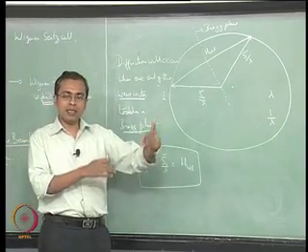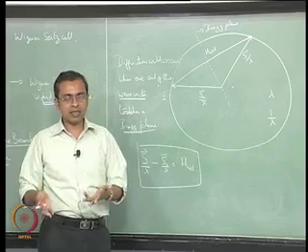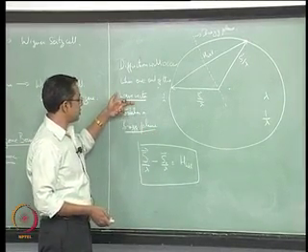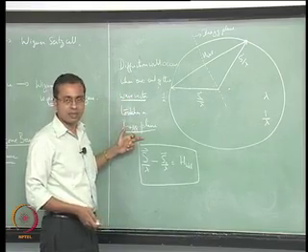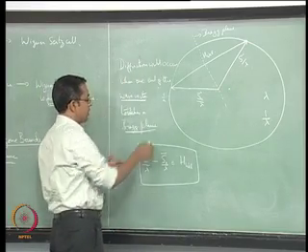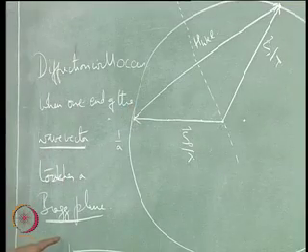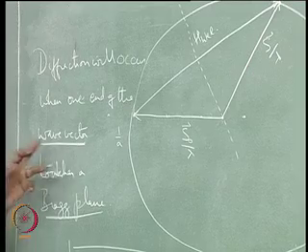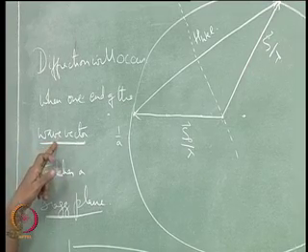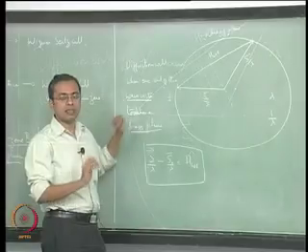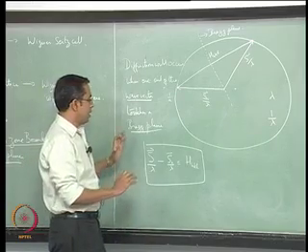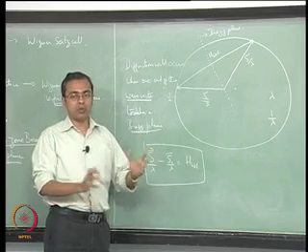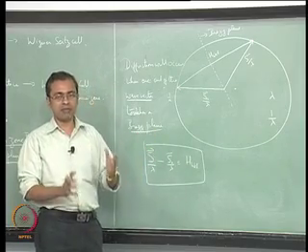Another piece of information is waves that are arriving at the sample or are in the sample. There are wave vectors with respect to those waves. So this is something associated with the wave, this is something associated with the sample. What we have written here is the interaction of that wave with that sample, and we find that whenever the wave vector touches a Bragg plane, or therefore whenever the wave vector touches the Brillouin zone, diffraction occurs. So this is the principal idea, the principal concept that we have narrowed down to.